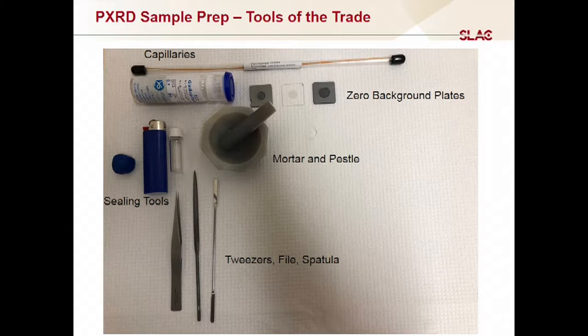So if you think about if you have plate-like crystals and you just kind of mound them up and then you smash them down, they're all going to align so that the plates are horizontal. If you have needle-like crystals, it will do more or less the same thing. The needles are going to align horizontally when you smash it down. That's not a good powder. You're not going to end up with particularly good data because you're going to have a large amount of preferred orientation that you then have to include into your model, which you would rather avoid. You can model these things, but it's much better to avoid them in the data collection and the sample prep than to deal with them after the fact.